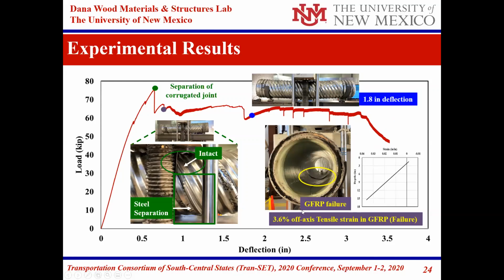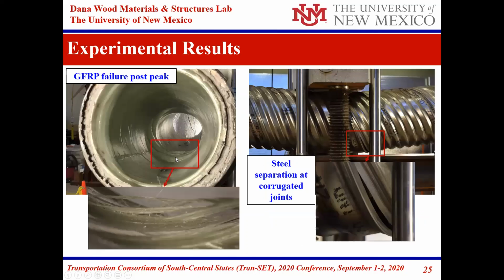Total deformation here was 1.8 inch, but the total is 3.5 inches, you can see. Again, this is a close-up to show you the failure in the glass fiber at the middle, which means complete force transfer between the glass fiber and the steel pipe. And the failure happening actually with the corrugated joint of the steel having separation here, and then resulting in failure in the GFRP.